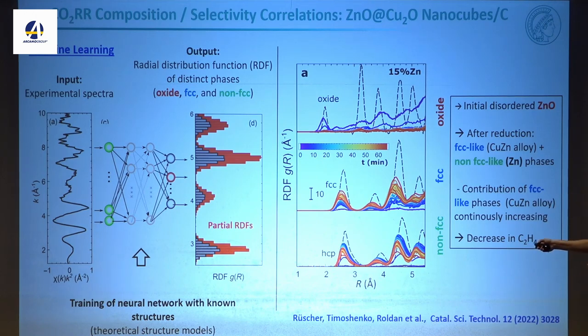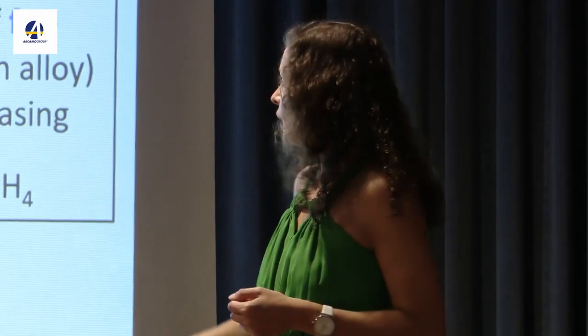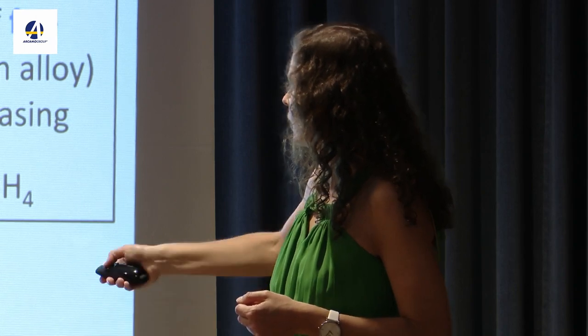So this is here the reaction time, and I can separate what will be the zinc oxide, I can separate what are the FCC-like alloy and non-FCC. And this is here as I'm running the reaction, when I'm seeing the deactivation of this catalyst, making less ethylene. And when we are making less ethylene, we are increasing this FCC copper zinc alloy, so we're making brass. And you see that you are decreasing this phase that will be the zinc oxide.